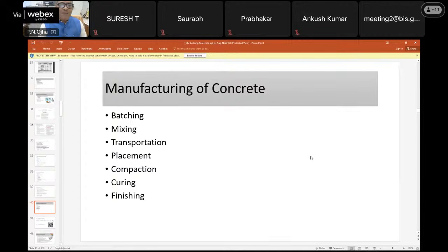So the manufacturing process means not only manufacturing, but the steps by which concrete is manufactured and used. The first is batching, preferably weigh batching, then mixing in the mixer, then transporting it to the site and placing it, then compaction of the concrete to remove the entrapped air voids, and then after a little bit of hardening, curing throughout, and then finishing.